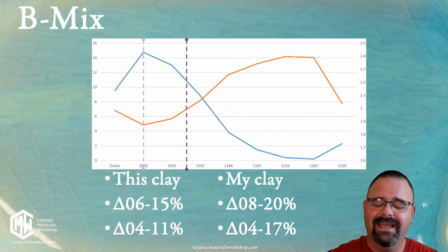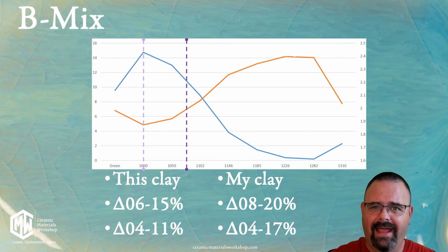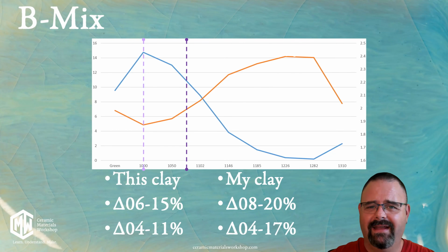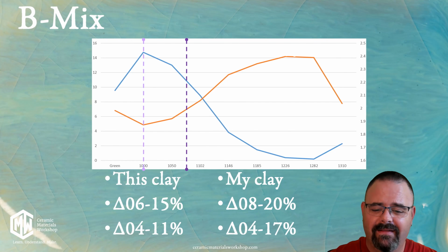Now, the other thing to understand is don't assume that all clays are going to benefit from the same bisque temperature. This is a firing curve from some B-Mix that was sent to me by my friend Stacy Morgan, and I ran its firing profile to check its absorption. The interesting thing is that on this B-Mix at cone 06, the clay body had 15% absorption, and at cone 04, it had 11% absorption. Now, once again, my clay body that I'm working with at cone 08 has 20 and at cone 04 has 17. So even two different clay bodies bisqued to the same temperature are going to have radically different applications.